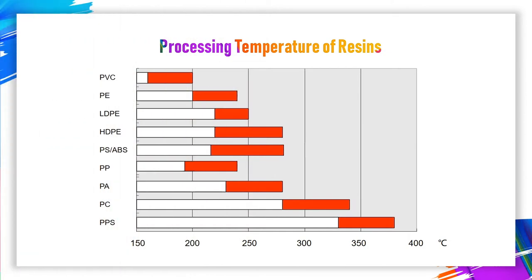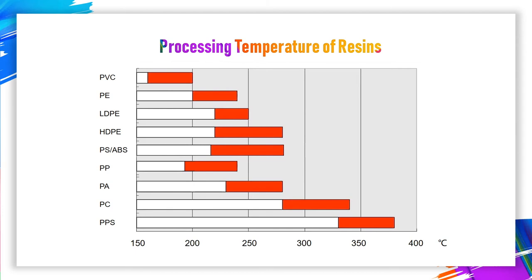For different types of plastics, their processing temperature is between 120 and 350 Celsius degrees. Hard and soft PVC and EVA need medium processing temperature, generally from 170 to 200 Celsius degrees. LDPE, HDPE, and PS are processed in a range of 200 to 260 degrees. The processing temperature of PA and ABS is above 260. Some plastics require particularly high processing temperature, such as fluorocarbons, polysiloxane, and newly developed high-temperature materials. The processing temperature of thermosetting resin is relatively low, but its processing time is longer. Therefore, the colorants need to meet the processing temperature requirements for different resins. The temperature ranges for different types of plastics are shown in the table.